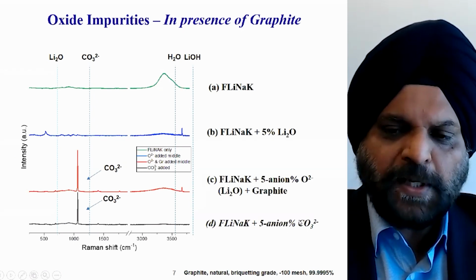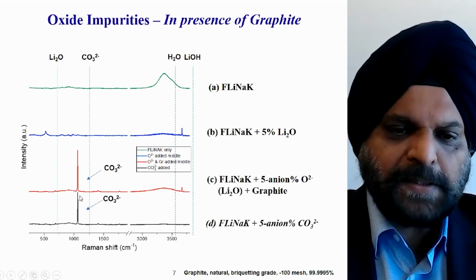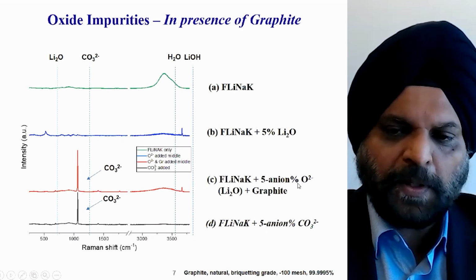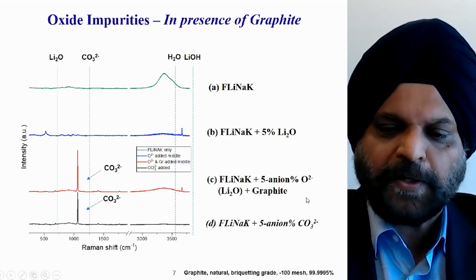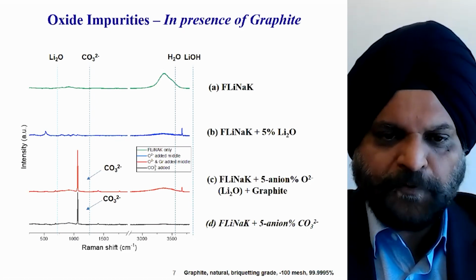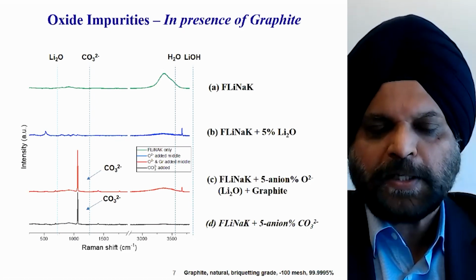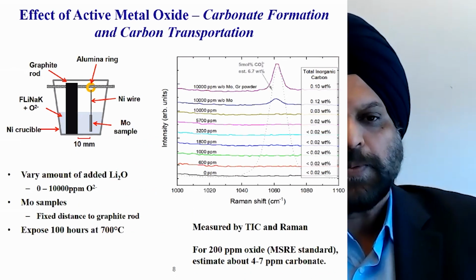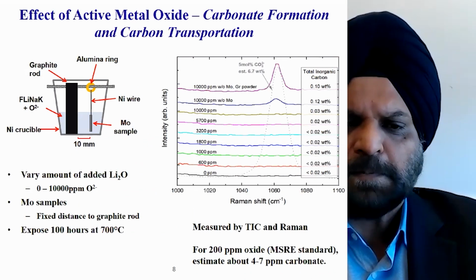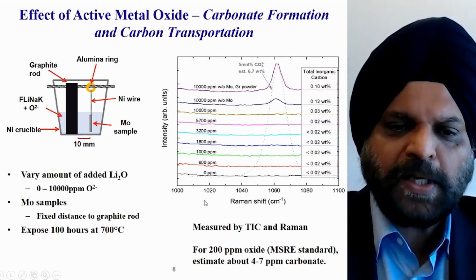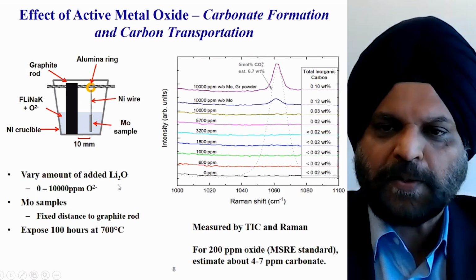And if we just directly add lithium carbonate, that peak is exactly the way it is if you add lithium oxide and graphite together. So with that proof that yes, we can form carbonates with reaction, we wanted to find out what is the minimum amount of oxide that is required before you actually start to see this carbonate.